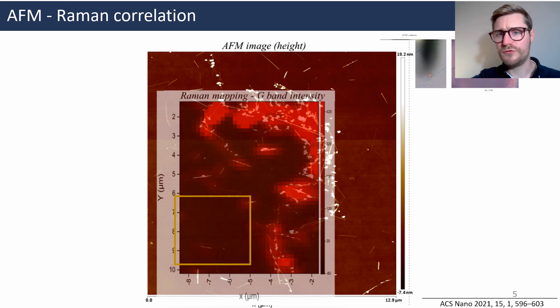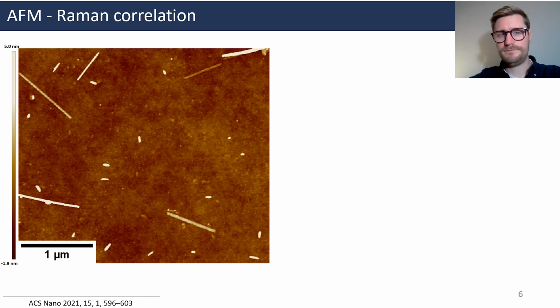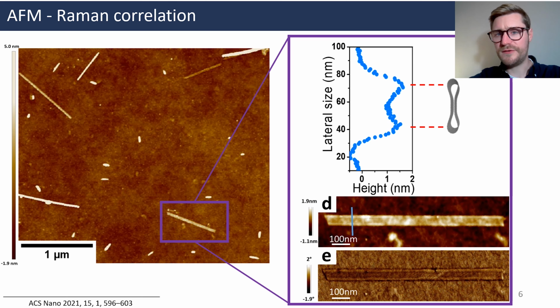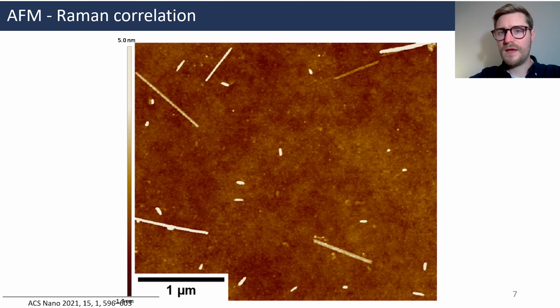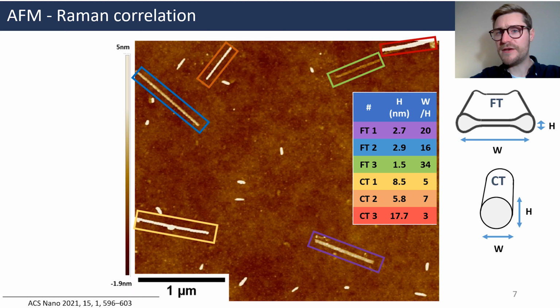Then we focus on a zone having a low density of nanotubes. Here's the zone. It contains six elongated objects. Among them, one is, for example, flattened, at least. In fact, a single-wall flattened nanotube can be seen as a bilayer graphene nanoribbon, which is closed on each border by two longitudinal cavities. We can clearly see on the AFM images and on the profile line the presence of those cavities. Actually, by measuring the height value of the six objects, it's possible to sort them into two categories, cylindrical or flattened.